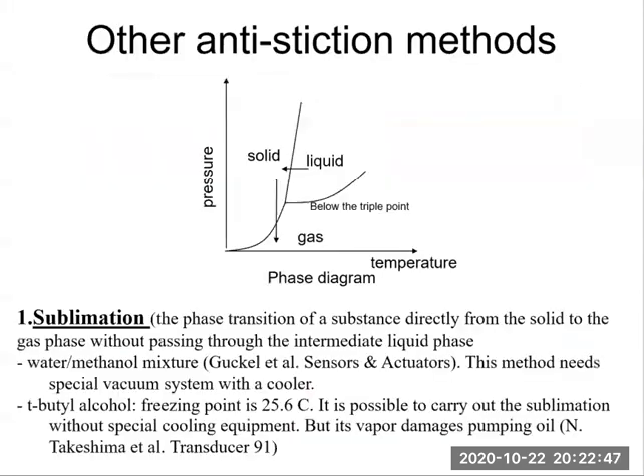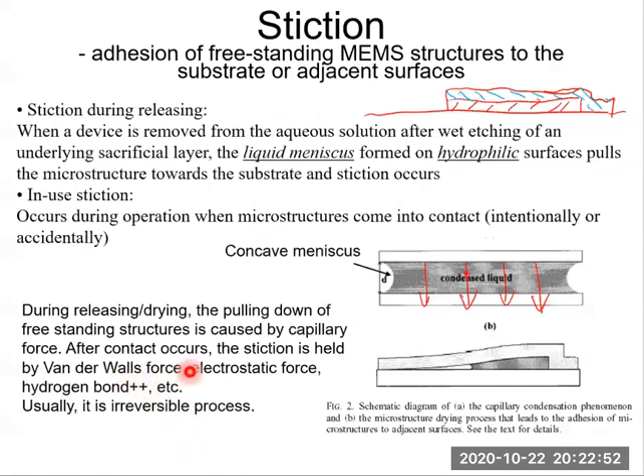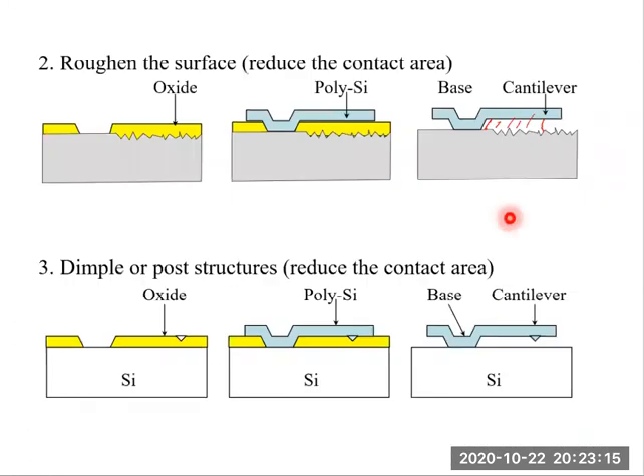Why? Right here, we state that the stiction is held by van der Waals force, electrostatic force, and hydrogen bonds. All these forces are proportional to the contact area. Namely, if the contact area is very small, those forces will be very small, so they cannot hold the cantilever. The restoring force of the cantilever itself will be greater than those holding forces due to the reduced contact area. So the cantilever can become freestanding again after the water or liquid completely evaporates. Questions?